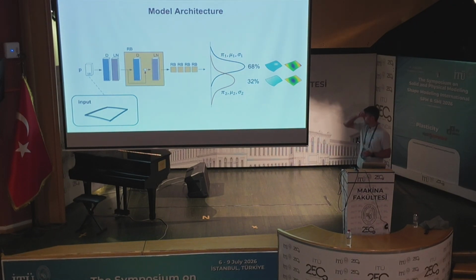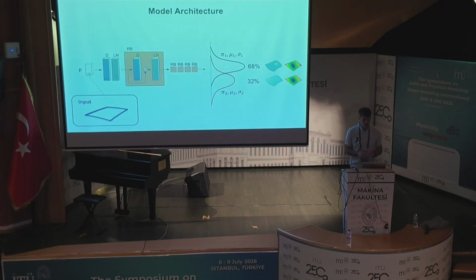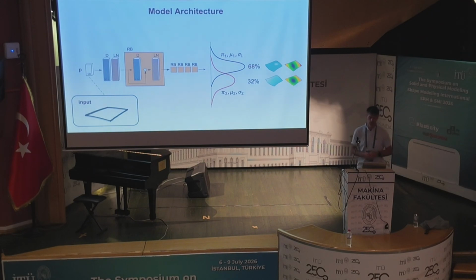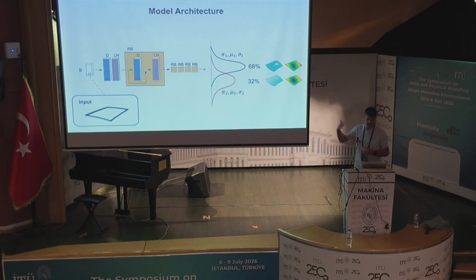What I want to mention here is that during the training process, we made two very interesting observations that go beyond just using a model to make things faster. First, we realized during experiments that the network allows us to discover stable states that were initially not in the training set. We then simulate these newly detected states to verify that this is truly a valid state. And if so, we add it back to the training database, thereby iteratively improving the results.